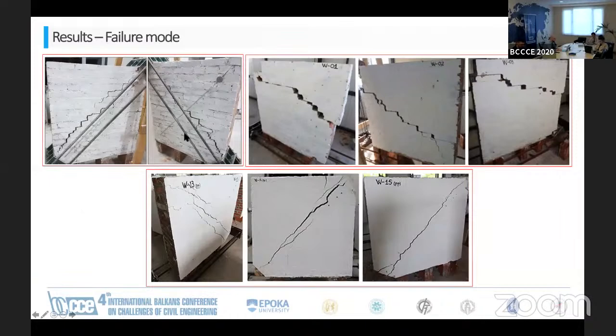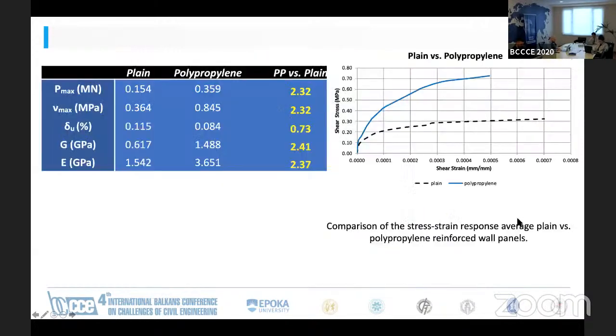In the first and second figure, it's both sides of the same wall that you can see the diagonal crack. In wall number 1, we could also see a part of it in a sliding failure. And then the other 2 walls again have failed in almost a similar way. Whereas for the polypropylene reinforced panels, we could clearly see a distinct, thick diagonal crack along the reinforced layer.